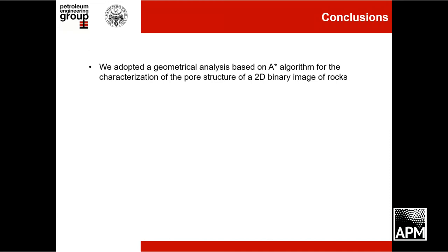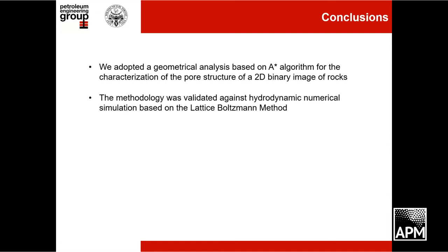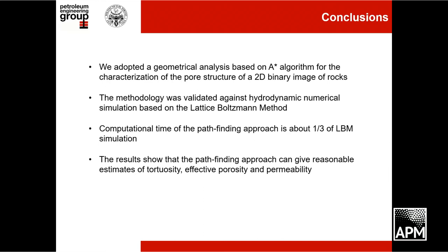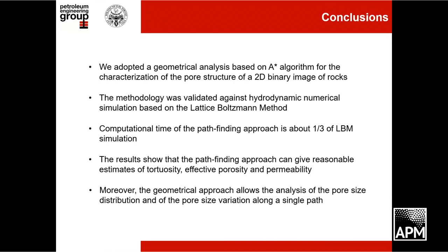In conclusion, we adopted a geometrical analysis based on the A* algorithm for characterization of the pore structure of a 2D rock image. The methodology was validated against a numerical simulation based on the Lattice Boltzmann method. The computational time of the pathfinding approach is about one-third of the Lattice Boltzmann simulation. The results show that the pathfinding approach can give reasonable estimates of tortuosity, effective porosity, and permeability. Moreover, from the geometrical analysis, we obtain the pore size distribution, the minimum pore size, and the pore size variation along a single path.